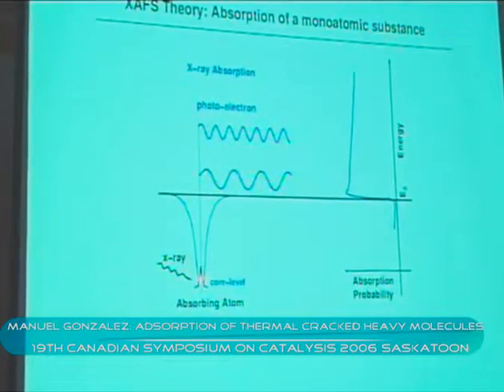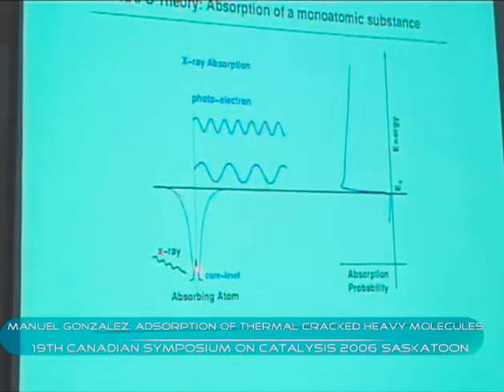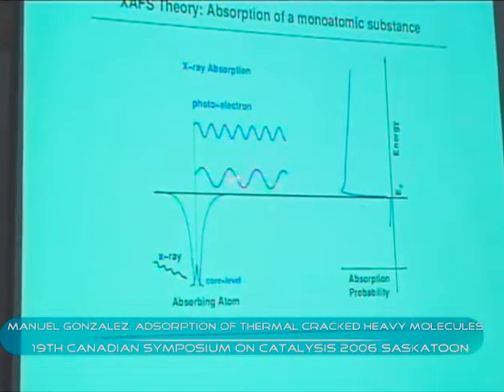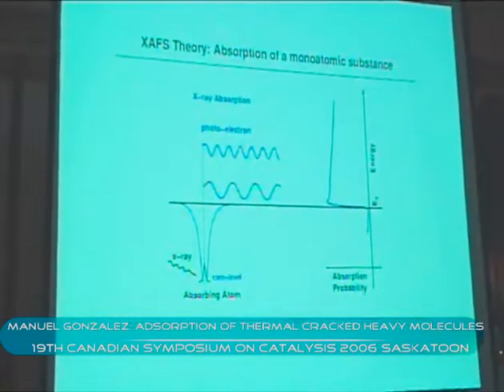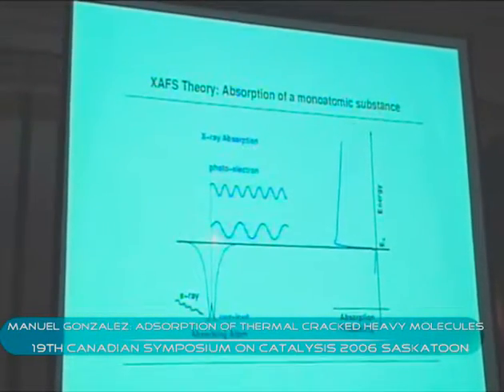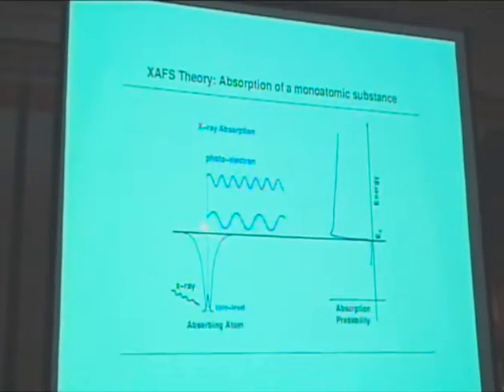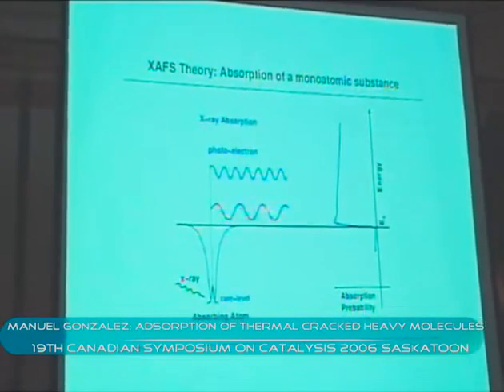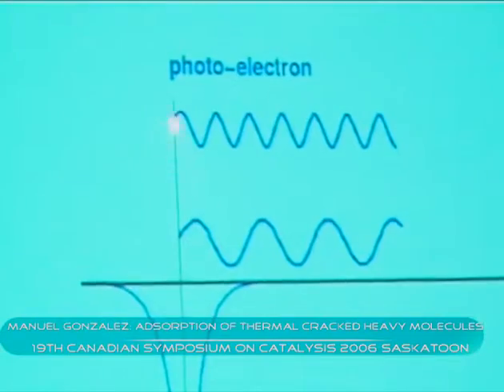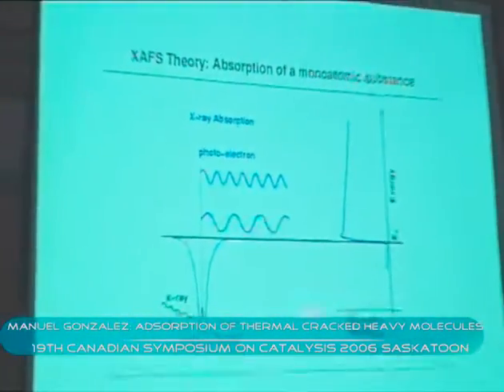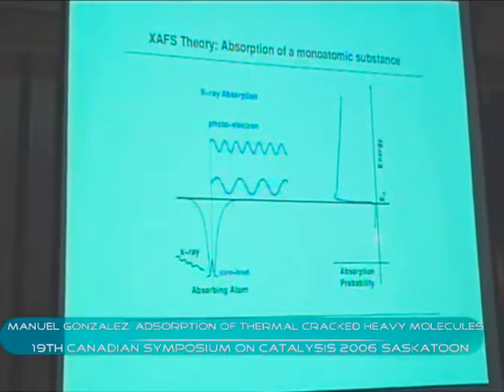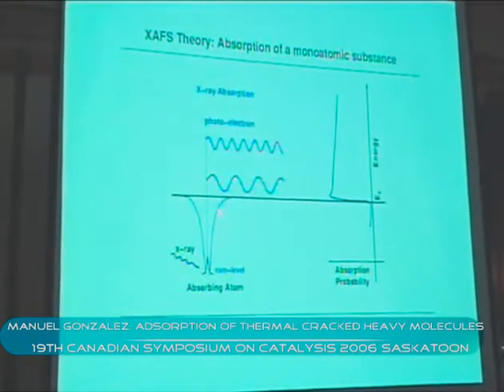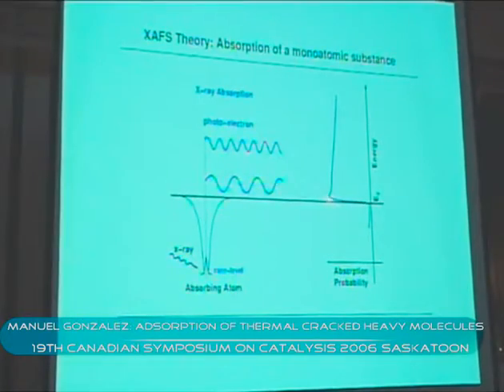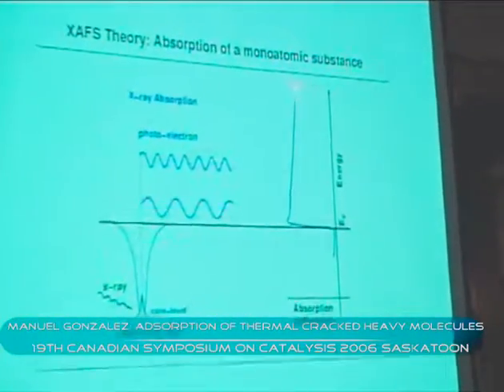And if it's an atom and it has no surrounding atoms, then the electron goes out, and in the classic picture you have a free wave going out. If you just bring it out above the Fermi level, then it has little kinetic energy, so it has a long wavelength. If it has a lot of kinetic energy, then it has a short wavelength. And what you will see then in the X-ray absorption is that if the energy is just enough to bring it out, you suddenly have an absorption, and from there on a slowly decreasing absorption coefficient.